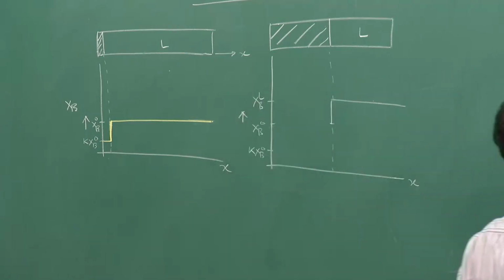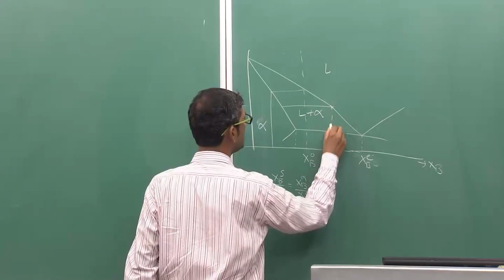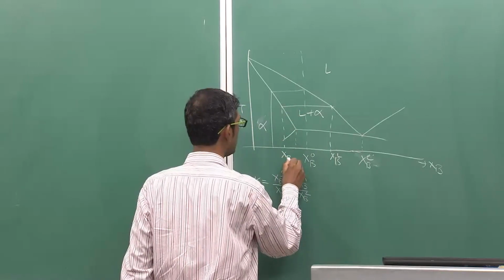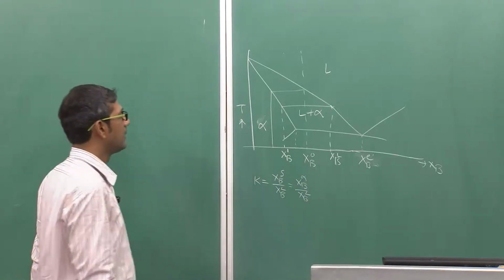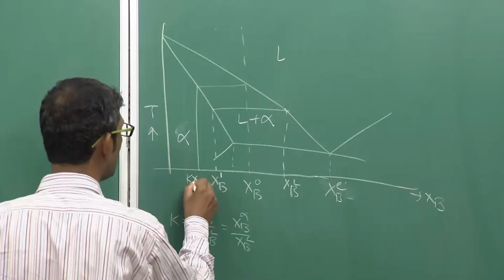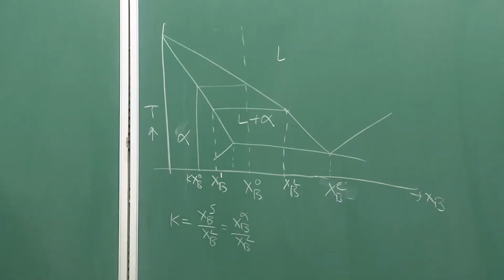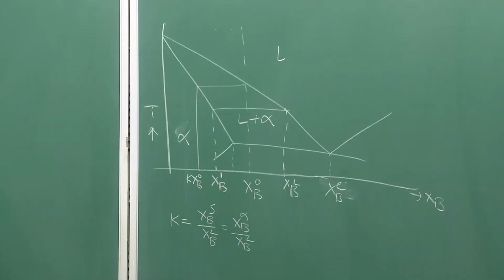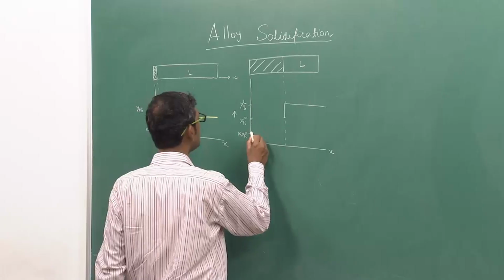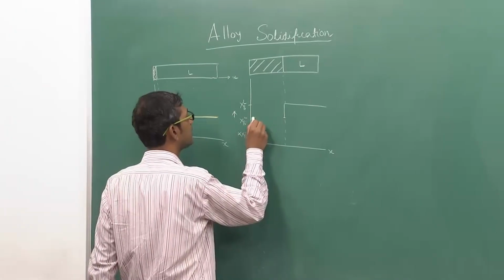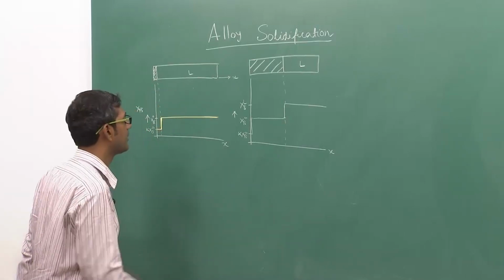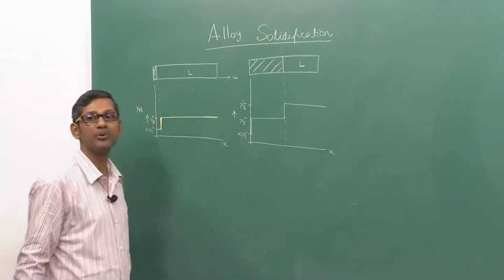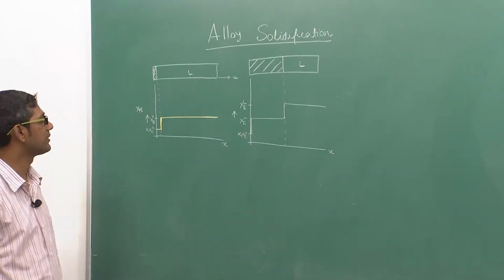As you see here, if I have some solid here, this is my Xpl, this is Xp0, and this is my Xp1 suppose. But initial solid has Kxp0, but because we are doing equilibrium conditions, this compositional difference will be completely annulled out. So, initially although there will be a little bit of a problem, it will go back and remain like this, okay. Slowly it will catch up. So, that means what? Solid will always have uniform composition of Xp0, okay, always.